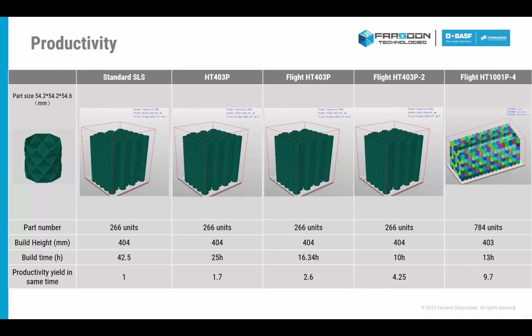So looking at our HT403, which is comparable to most mid-size SLS systems currently on the market, we can find that although, yes, we are able to nest 266 parts in the build envelope, we are also looking at a 25-hour build, which is better than 42 hours, but still not quite ideal in a manufacturing type environment. So that's where our single laser flight system comes into play, cutting build time down to a little over 16 hours, giving us 2.6 times the productivity yield over a standard SLS system.